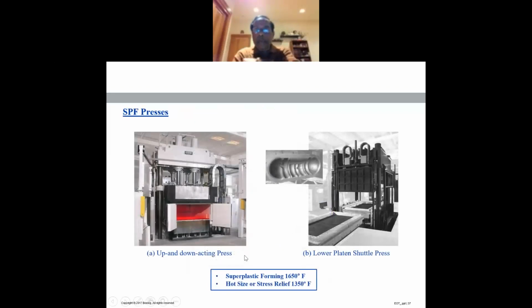Here are a couple of presses I'm showing you. Figure A is called the up and down acting press. Figure B shows a lower platen shuttle type of press. This is an example of a superplastic formed part. Superplastic temperature is typically 1650 degrees Fahrenheit for titanium. After the forming you need a stress relieving operation to remove all the internal stresses developed, and the stress relieving temperature is typically 1350 degrees Fahrenheit.